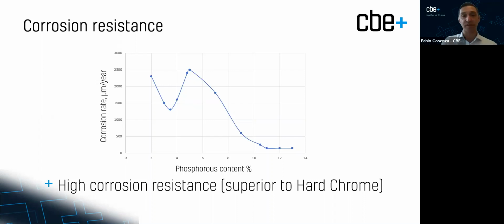In terms of corrosion resistance, you can see on this chart that we can greatly reduce the corrosion rate in microns per year by adding phosphorus to the plating bath. Above 10% content in phosphorus, we really can reduce the corrosion rate to virtually nothing. The performance in this case is far superior to that of hard chrome.